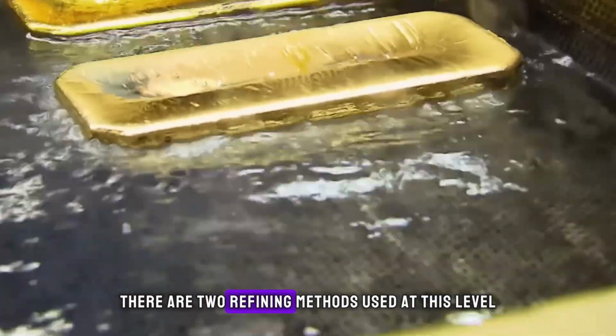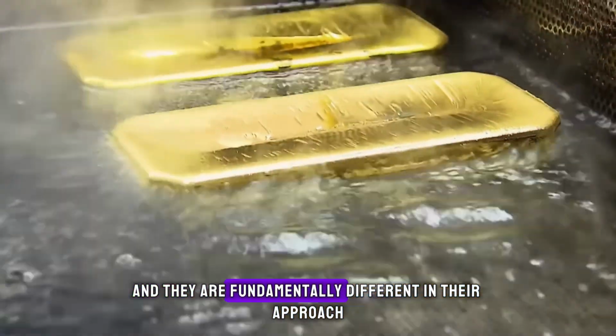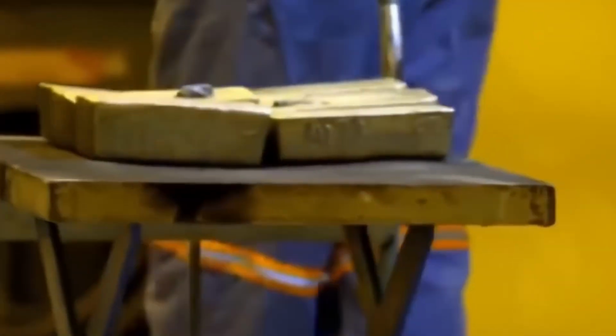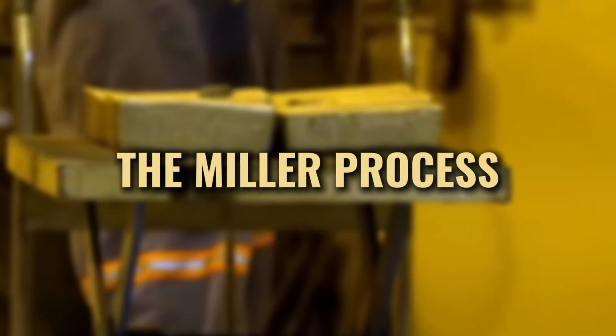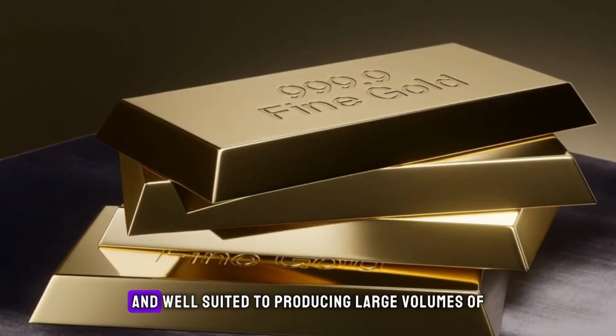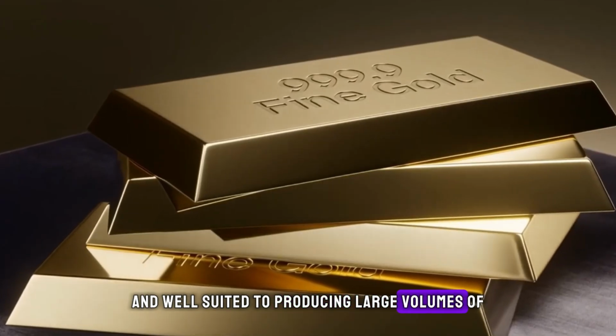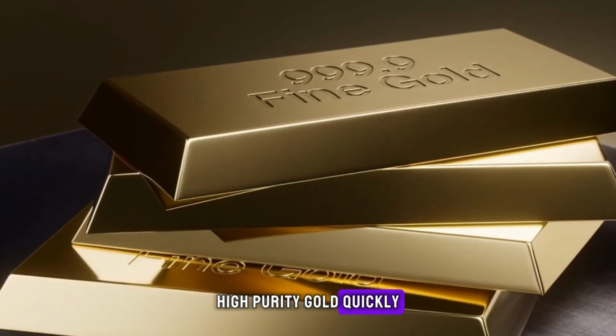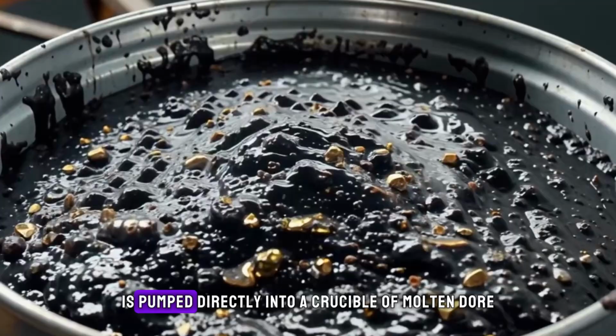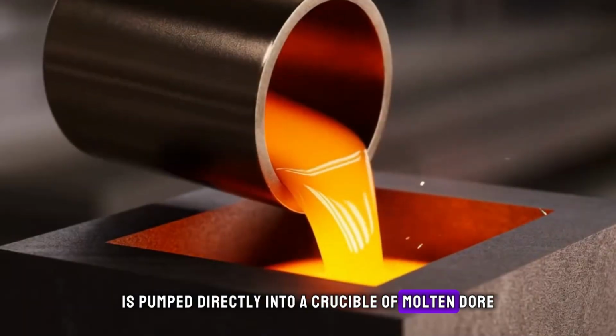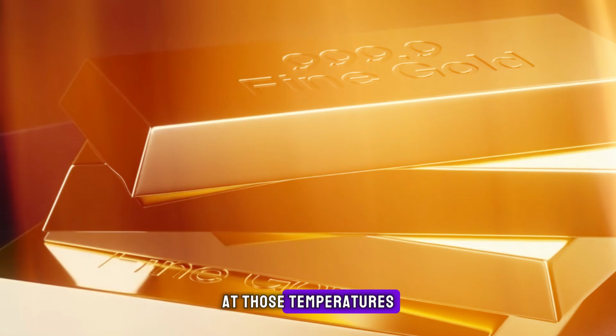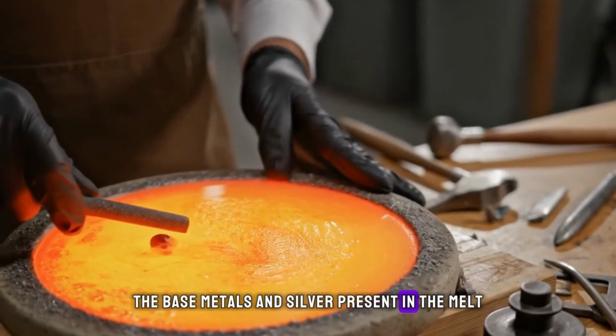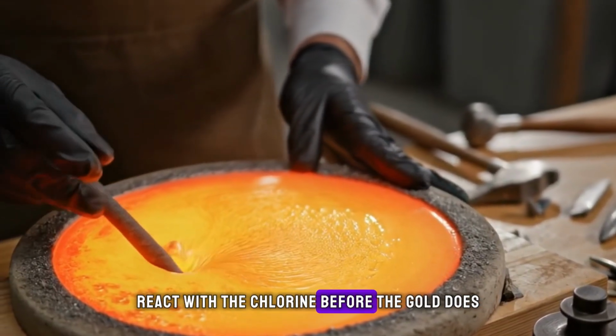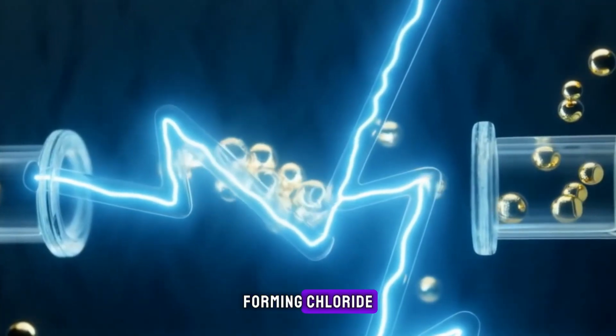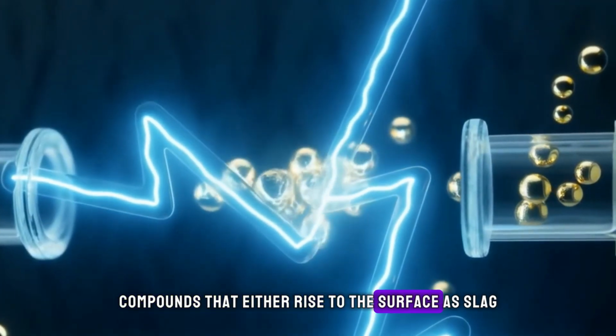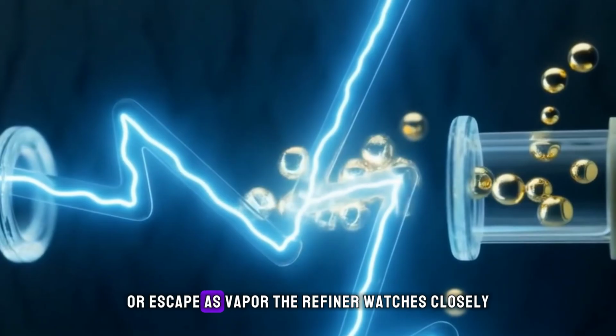There are two refining methods used at this level, and they are fundamentally different in their approach. The first is the Miller process, which is faster and well suited to producing large volumes of high-purity gold quickly. Chlorine gas is pumped directly into a crucible of molten doré. At those temperatures, the base metals and silver present in the melt react with the chlorine before the gold does, forming chloride compounds that either rise to the surface as slag or escape as vapor.